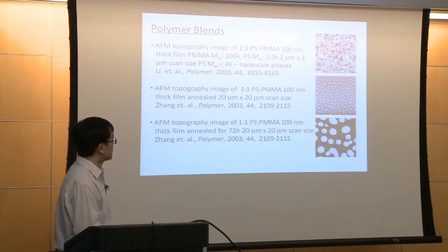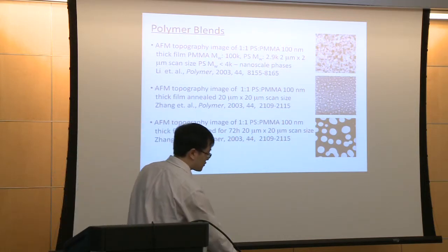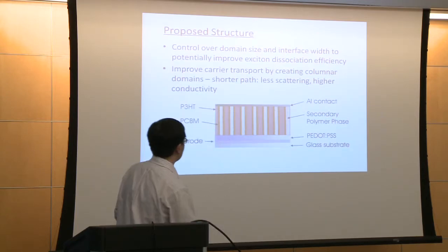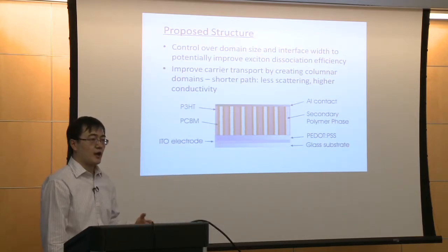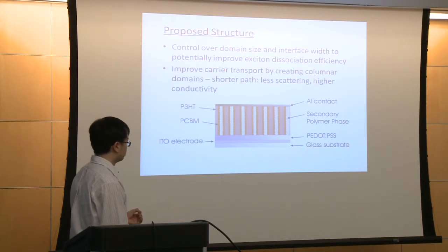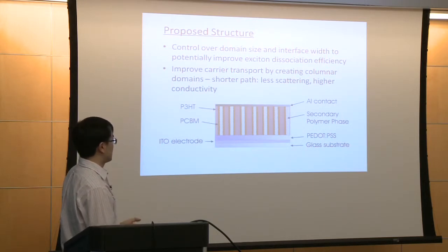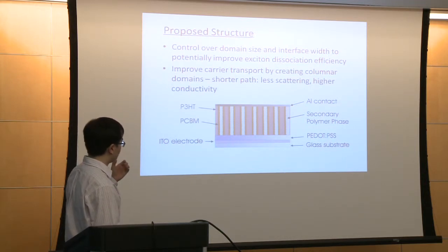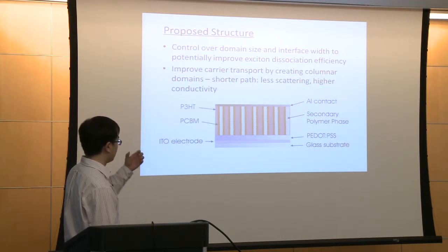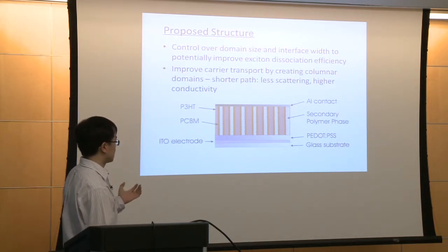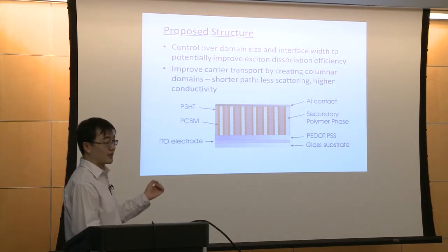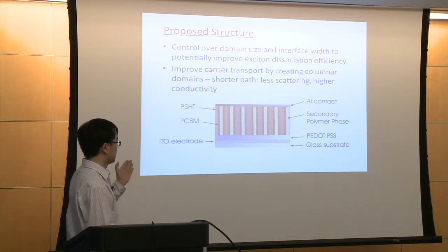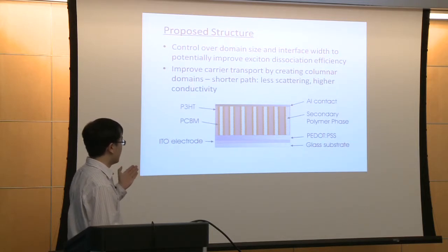So here we are considering whether we can introduce a secondary polymer into the active layer to help generate the column structure. So this is the structure we want to build up. Basically the P3HT, which is the electron donor, will be made as columns dispersed in the secondary polymer phase. And the PCBM, which is the electron acceptor, will be segregated along the interface between the P3HT and the secondary polymer.